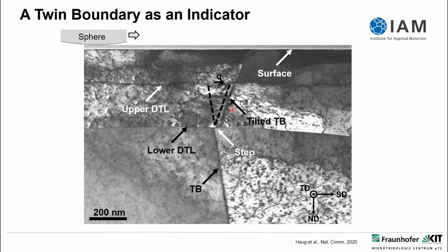Well, we see that we don't just tilt the twin boundary, we see that there's a step, right? We also shift the twin boundary. Now, what this twin boundary allows us to do is act as something like an indicator, or a silent witness, to the processes that happened under this one trace. Processes that, if we look at a structure without a grain boundary as I've shown you before, we might have missed, we might not have seen them.